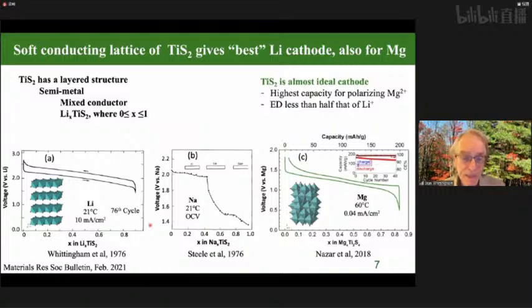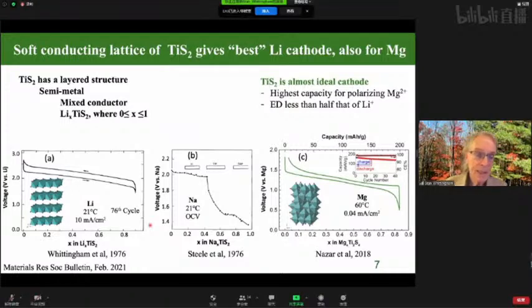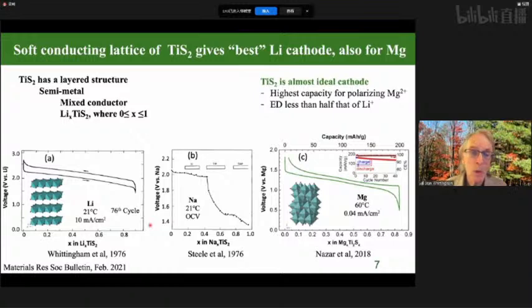In the middle there is the same behavior for sodium. This is now open circuit voltages. You can see this is much more complicated. Whole series of phases formed, as opposed to lithium where it's a single phase for all compositions. And on the right-hand side is the best data available to date for a magnesium TiS2 or any magnesium battery. And this is with TiS2, and this is the work of Linda Nazar at Waterloo. And no one has got this many cycles in a magnesium cell, and essentially 100% Coulombic efficiency.